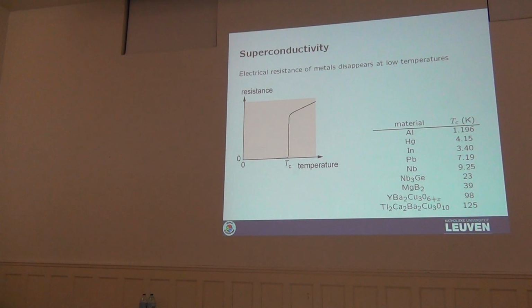So this experiment was done in the UK for several years, and then it was stopped because of a strike of transport workers. They couldn't deliver liquid helium, so they couldn't cool it down. So they estimated from these few years, given the resolution of the best voltmeter they used, that the decay time of the superconducting current in a superconducting ring is comparable with the age of our universe, something like that. So it's really a quantum state which is non-dissipating.